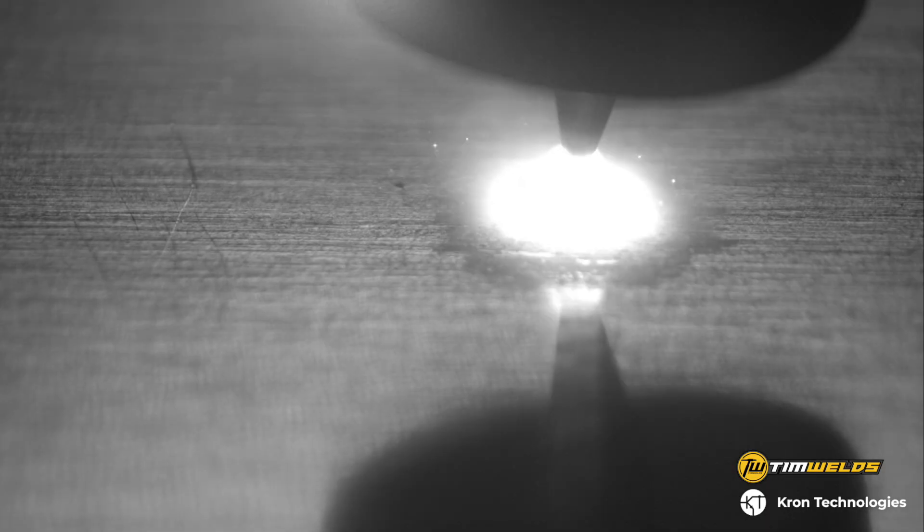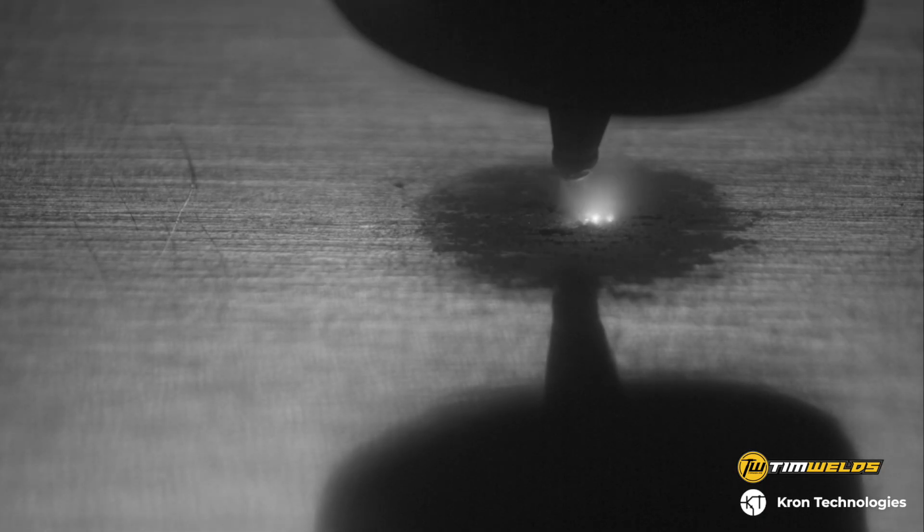That's where the alternating current is actually etching and cleaning the surface of the aluminum to give clean metal for a sound weld. Let's watch what happens here when we move in closer. When the arc starts, most machines will give a huge rush of current to give a nice crisp start.